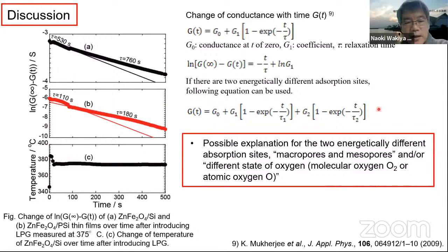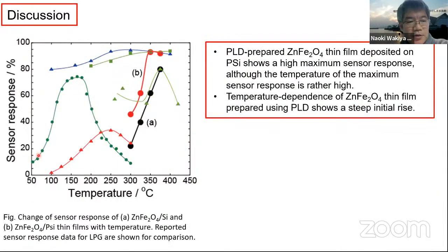So using this analysis, we can obtain a possible explanation for the two energetically different absorption states. This change may be obtained from the different absorption sites, macropores and mesopores, and different states of oxygen. It means molecular oxygen O2 or atomic oxygen O is responsible for this slope change. Anyway, zinc ferrite shows this kind of properties, and this is the change of the sensor response with temperature.